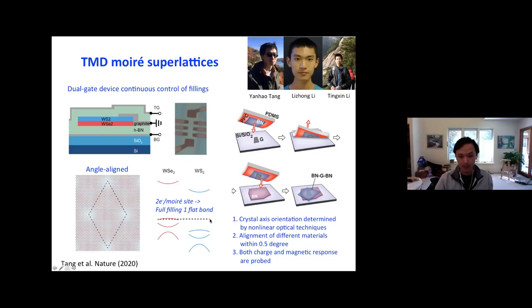And the convention that I will use in the following talk is that if you have one electron per moiré site, we call that a full filling of the moiré superlattice. That's filling factor equal to one, but it corresponds to half-filling of the first moiré band. And only if you put two electrons on each moiré site, and you get the filling factor equal to two, then you get a full filling of the moiré flat band.